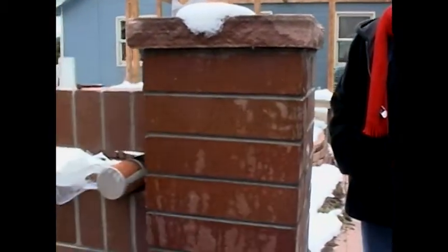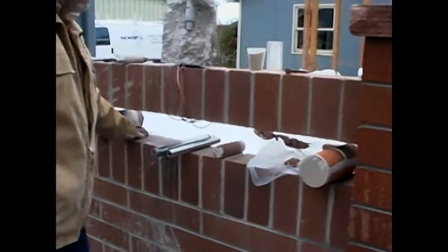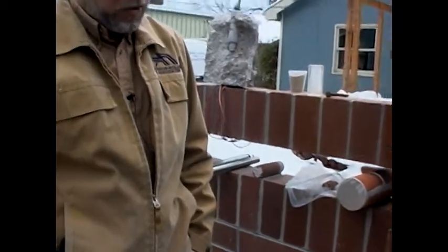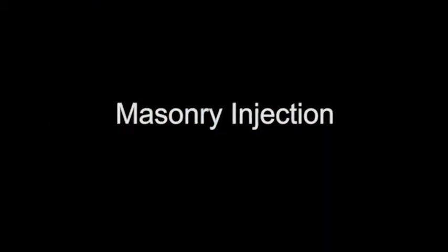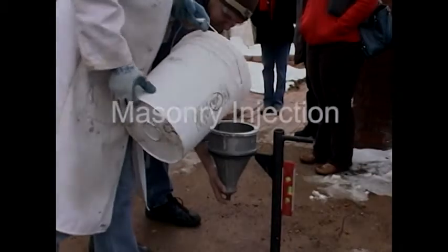I think we just finished a project at New York City Hall where we're injecting joints between stair treads, and they were 1/16 of an inch to 3/32 of an inch, and big, long stair treads, and it's pretty easy. I think our maximum penetration is in cracks about 0.07 of an inch and wider, although I've seen it in cracks much smaller. They'll fill it up, stop it, they'll use a stopwatch.